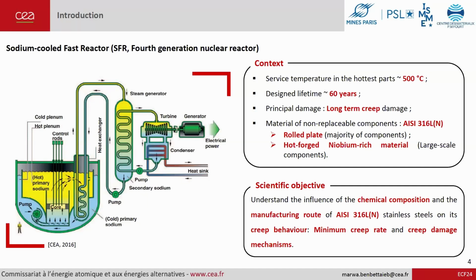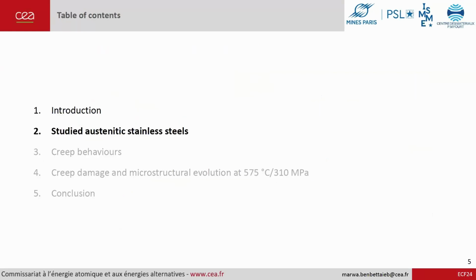Many manufacturing routes are used here, so the majority of our components are rolled, and the large-scale components are hot forged, adding a small amount of niobium to prevent grain growth during the manufacturing route at high temperature. And so our main aim here is to understand the influence of the chemical composition and the manufacturing route of the studied steels on the creep behavior, mainly on the minimum creep rate and the creep damage mechanisms.